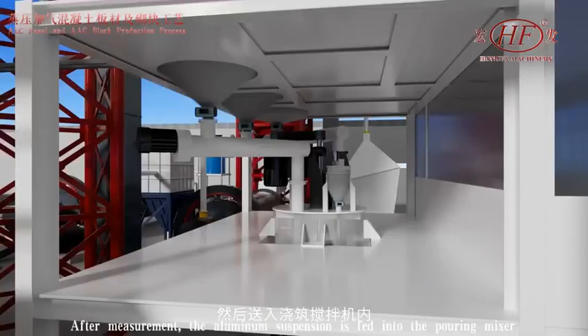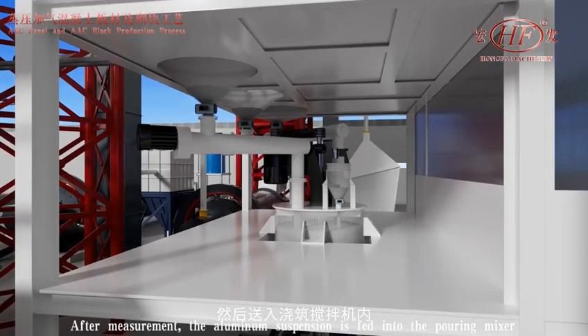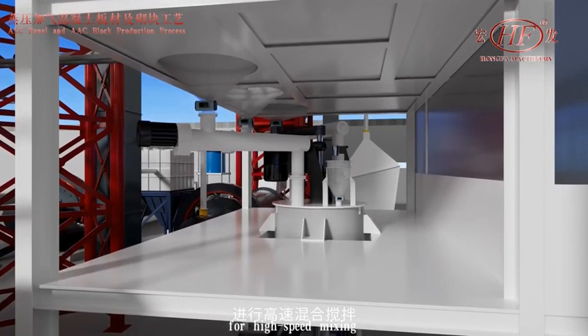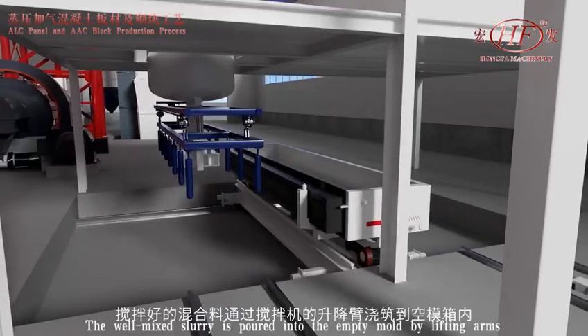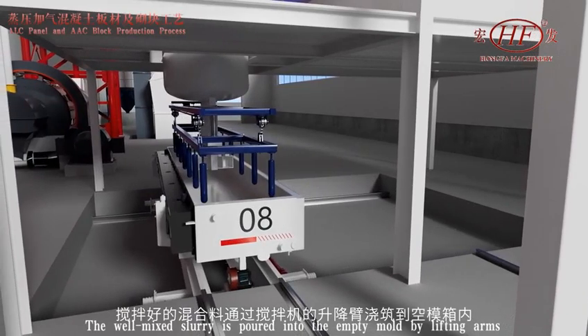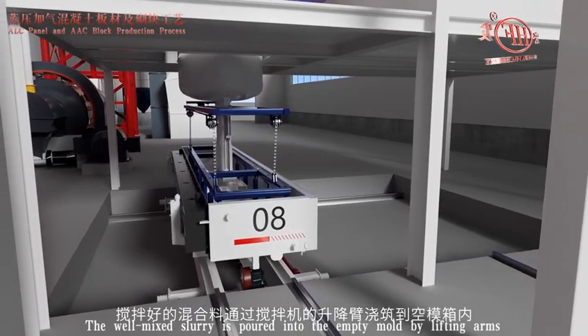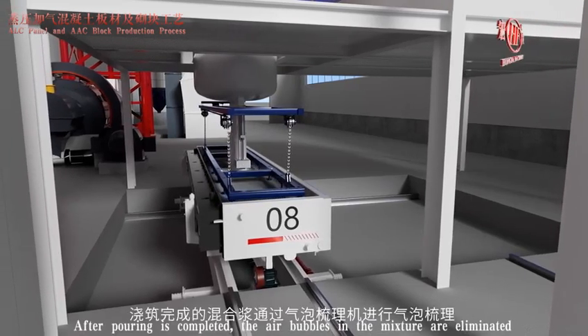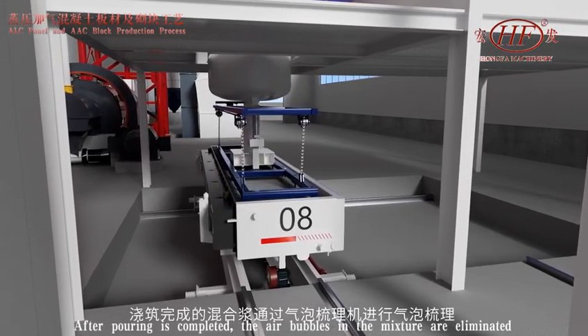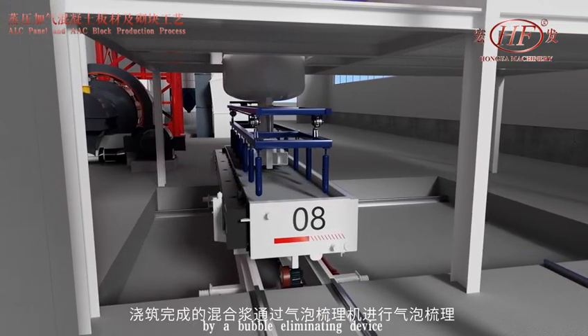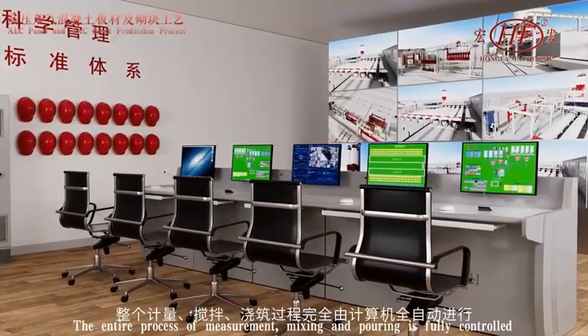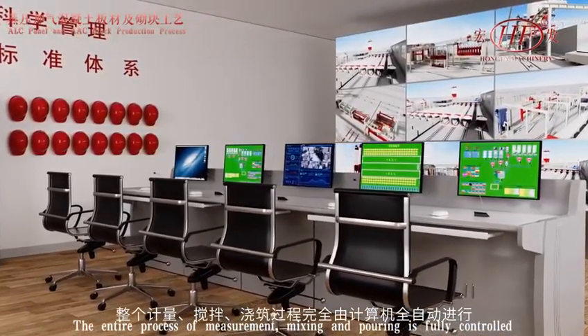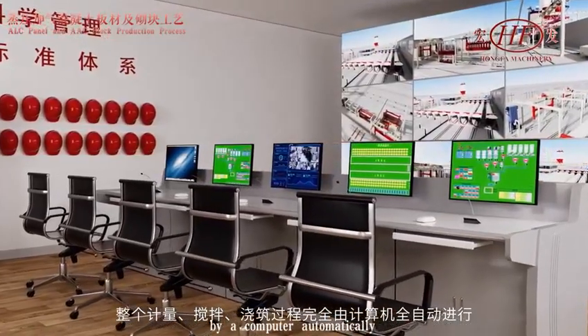After measurement, the aluminum suspension is fed into the pouring mixer for high-speed mixing. The well-mixed slurry is poured into the empty mold by lifting arms. After pouring is completed, the air bubbles in the mixture are eliminated by a bubble eliminating device. The entire process of measurement, mixing and pouring is fully controlled by a computer automatically.